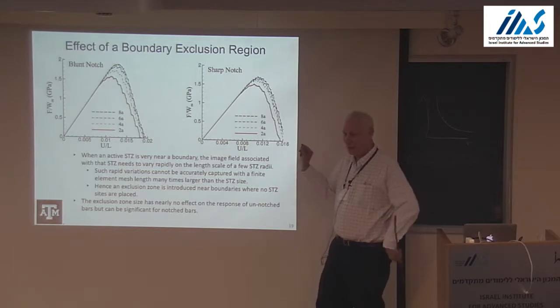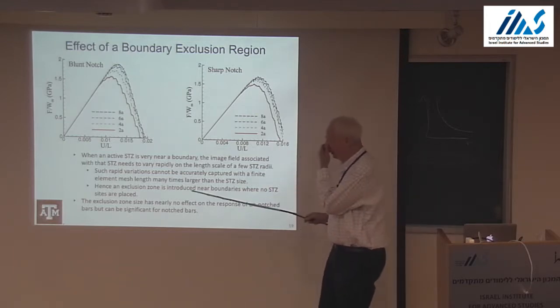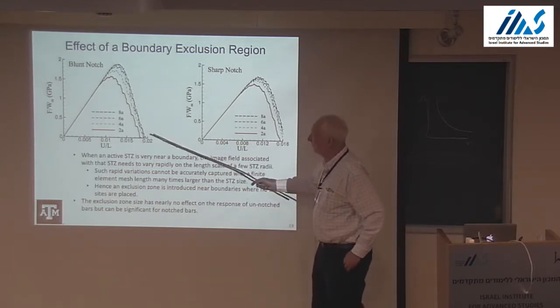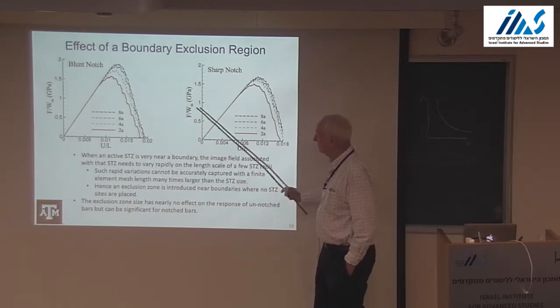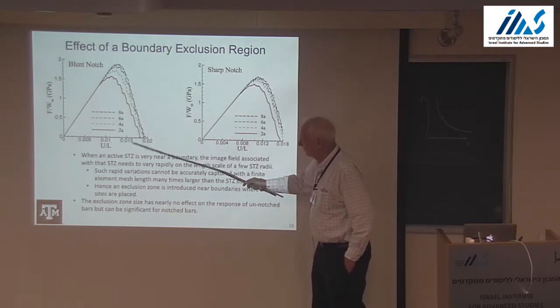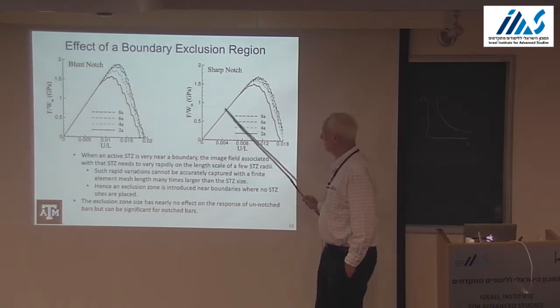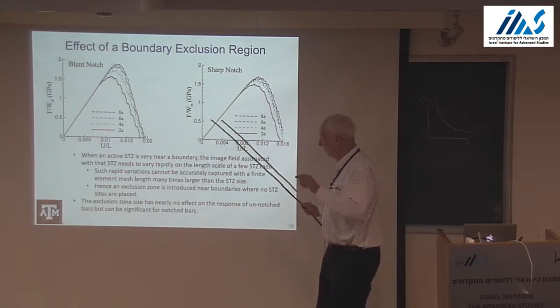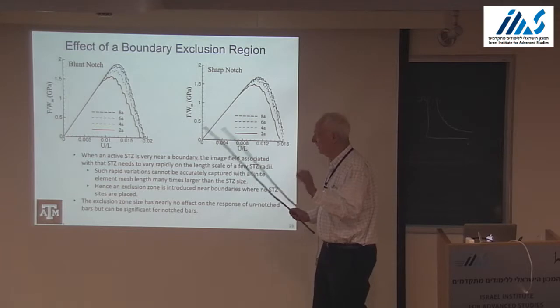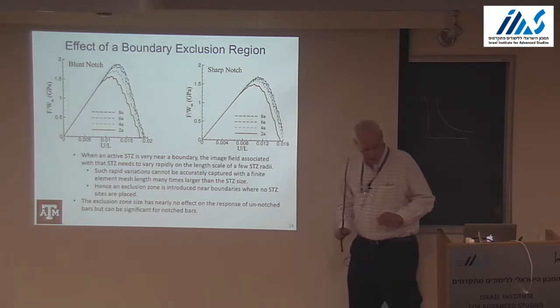So we leave an exclusion zone now. We know how to fix that. But for now, and these are the worst cases, we leave a zone around the notch, around the free surface, where no STZ activation is allowed.